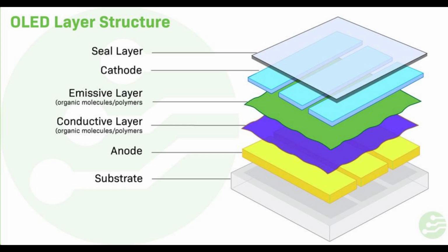Typical polymers used in PLED displays include derivatives of poly(p-phenylene vinylene) and polyfluorene. Substitution of side chains onto the polymer backbone may determine the color of emitted light or the stability and solubility of the polymer for performance and ease of processing. While unsubstituted poly(p-phenylene vinylene), PPV, is typically insoluble, a number of PPVs and related poly(naphthalene vinylene)s, PNVs, that are soluble in organic solvents or water have been prepared via ring opening metathesis polymerization.